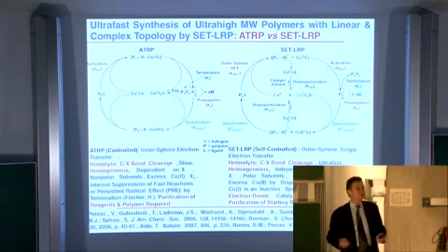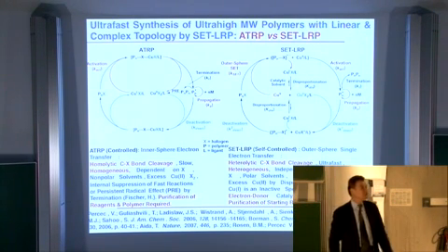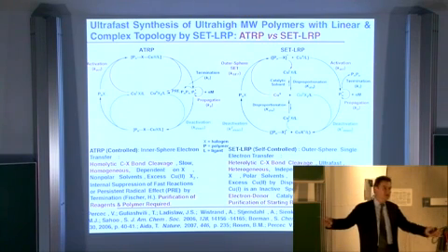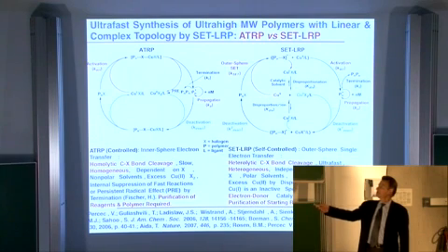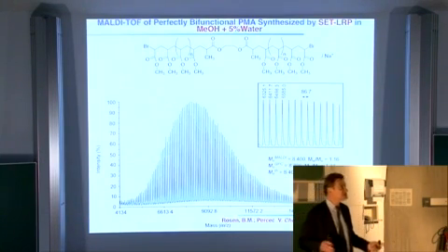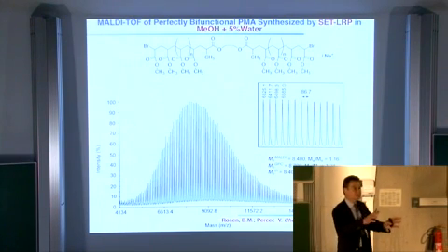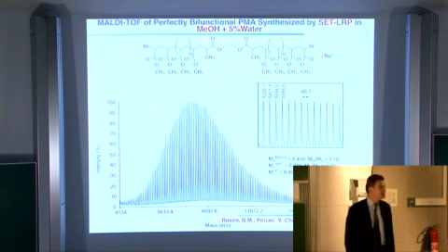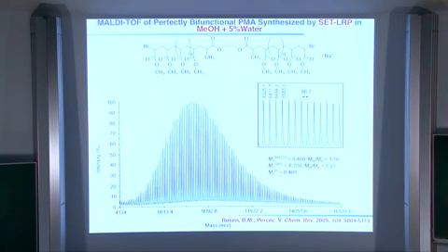It doesn't require the purification of any reagents because copper-0 can first consume the oxygen from the reaction mixture. It is the classic BASF catalyst that is used in all glove boxes, and the process doesn't require the purification of the reagent at the end, and so on and so forth. So to conclude this part, I'm going to show you the real slide that is most significant about this methodology. You can make polymers that resemble proteins, but are not like proteins.